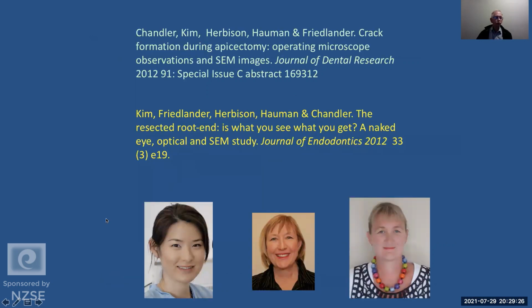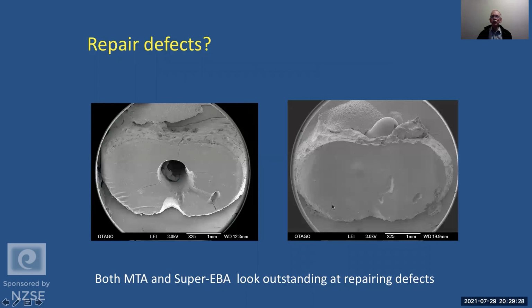And when we took the picture again, you can see the MTA made the most amazing job of filling in the defect. So it is quite exciting to see the quality that you can get with your condensation of root end filling materials. And we also used Super EBA, which people nowadays probably wouldn't use, but we had very, very similar results with Super EBA.